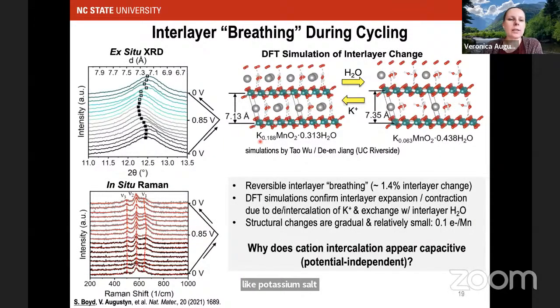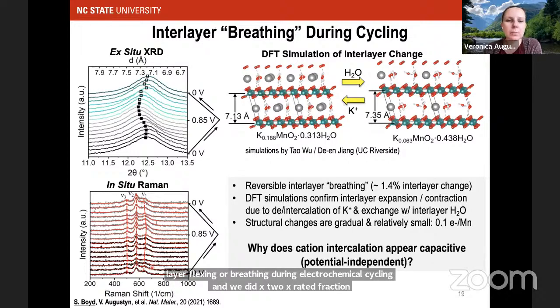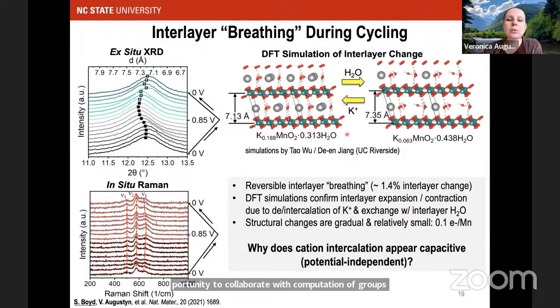So the insertion part, whether we're getting insertion, was also verified through looking at the structural changes of the material, essentially the interlayer flexing or breathing during electrochemical cycling. And we did ex situ X-ray diffraction as well as in situ Raman spectroscopy that showed that we had this 1.4% interlayer change. And DFT simulations, this is where we have that nice opportunity to collaborate with computational groups, showed that indeed the magnitude of changes that we were observing could come from a mechanism whereby potassium cations, when they deinsert, are replaced by water molecules. And that leads to structural changes that are gradual and relatively small, with about 0.1 electrons per manganese distributed through.